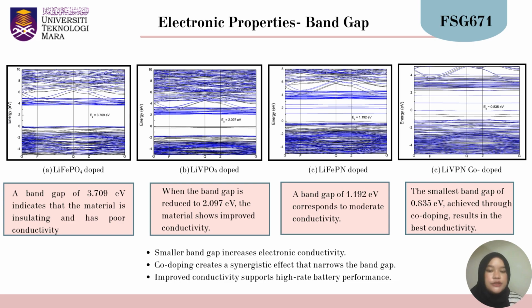Now, I will explain the electronic properties of my study, focusing on the band gap and how it affects conductivity. A smaller band gap means better electronic conductivity, which is important for lithium-ion battery performance, especially during fast charging and discharging. In this study, I used DFT calculations to check the band gaps of pure and doped LiFePO4. The pure LiFePO4 has a band gap of 3.709 eV, which makes it an insulator with poor conductivity. After vanadium doping, the band gap drops to 2.097 eV, showing better conductivity, and with nitrogen doping, it decreases further to 1.192 eV, improving it more.